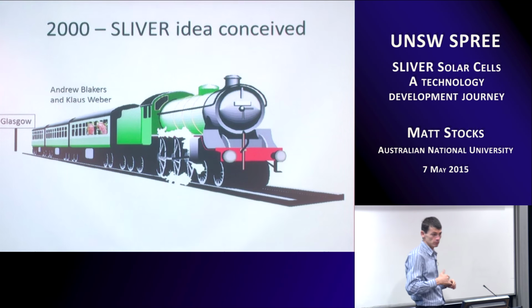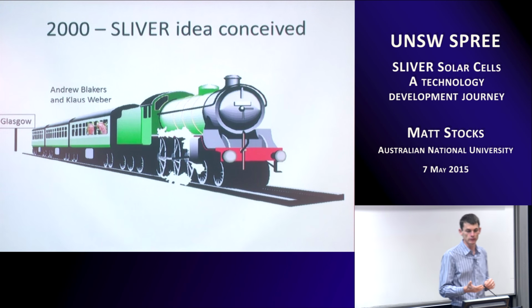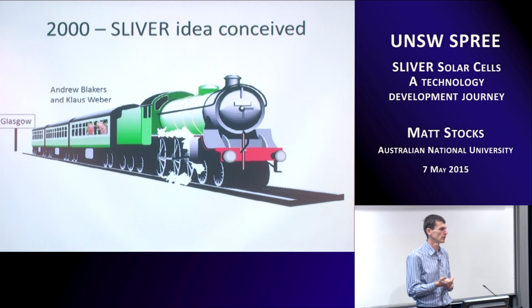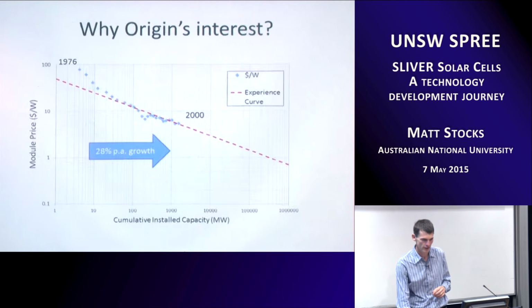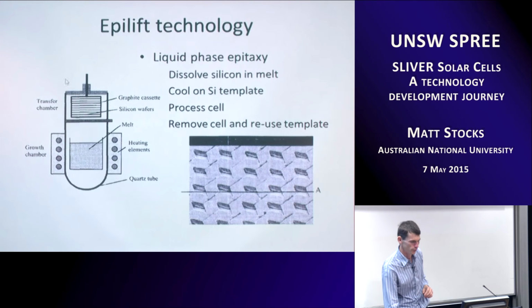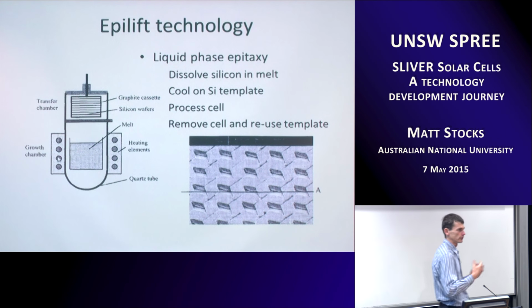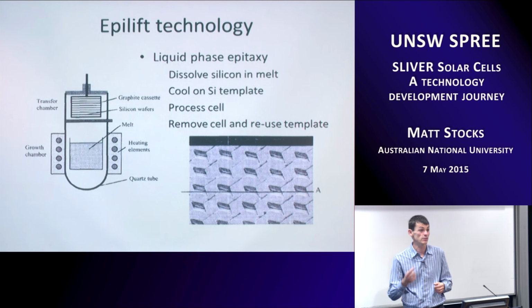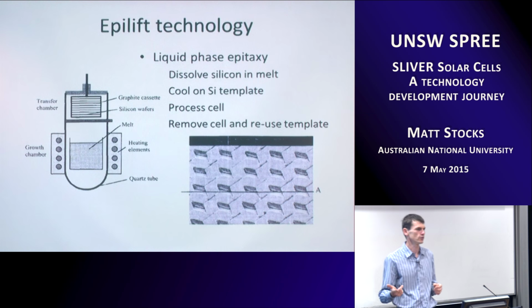So what happened after that? Epilift progressed quite well. We were going through to 2000. And then the decision was really around how do we scale this thing up? So what we had there was a technology which required custom manufacturing tools, in that we had to design and build the tool which was going to take multiple wafers, insert them in this metal melt, grow our silicon, and then get them back out again reliably. And we had to be able to do this again and again and again, because there was only value in it if we could reuse that template multiple times.